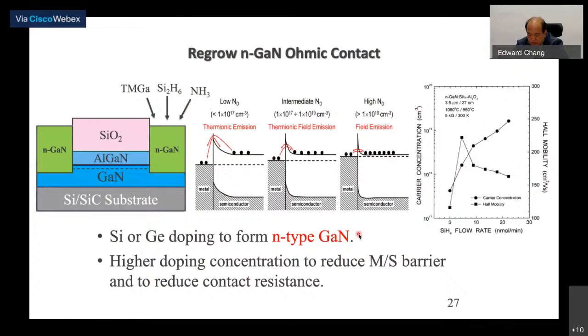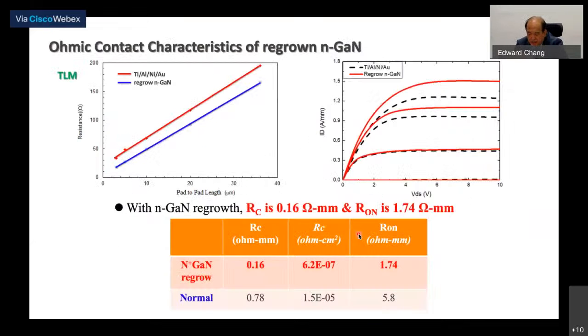So ohmic contact resistance, okay, can be improved by regrowth of the GaN nitride, because if you are just growing without any dopant, then your ohmic contact works, but the contact resistance is not low. But if you etch some part away, the ohmic area, and regrow the GaN nitride, then you can get very good contact resistance, okay. And this is the data for the technique we use, just using titanium, aluminum, nickel, gold, and then we regrow the GaN nitride. Then we get the contact resistance reduced to 0.16, okay, and then the R-on is 1.74, okay.